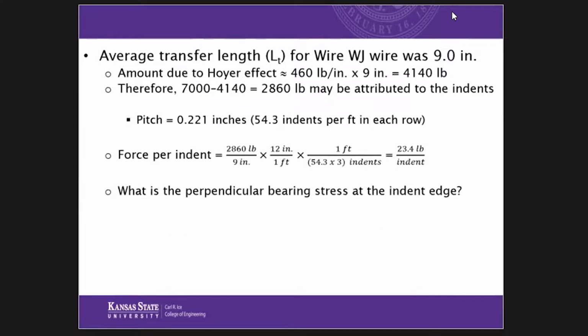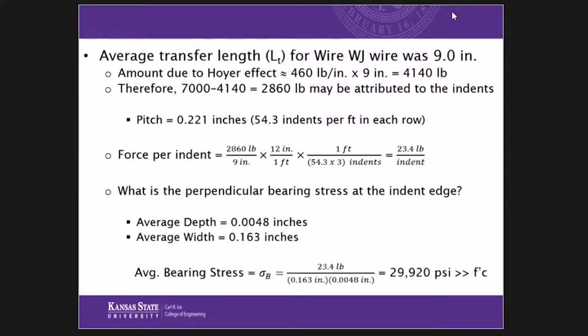I then ask, what would the bearing stress be on that individual indent? So I can take that force and divide that by the depth and the width of the indent, and I get a bearing stress of almost 30,000 PSI. What does that mean? It means the concrete crushes, right? And for the longest time, I started thinking about sidewall angles and get this idea of rigid body sliding, and a shallow sidewall angle is going to have more radial force. And I don't think that's true at all, because the concrete's crushing. And when we crush concrete, it has to be displaced, and it can't go inward, so it goes outward.